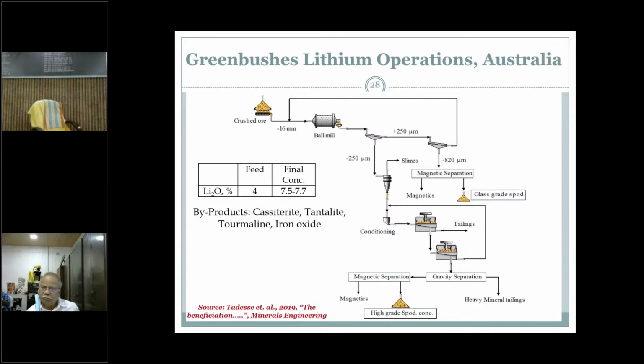Of course, a couple of examples from the Greenbushes operations in Australia. Here, the feed contains about 4% Li2O, and it is again subjected to size reduction with a ball mill. Here they are operating at a somewhat coarse size, around 250 microns, which will be subjected to magnetic separation. Magnetic impurities will be removed, and the spodumene concentrate that they get in the magnetic separator will be used as glass grade spodumene, as it is called. The fines fraction, about minus 250 microns, will be subjected to a cyclone followed by two-stage flotation, gravity concentration, and magnetic separation.